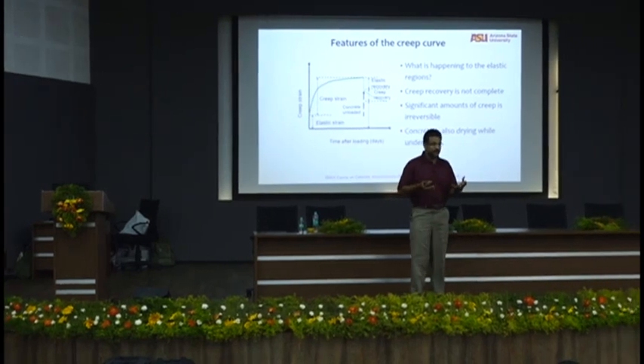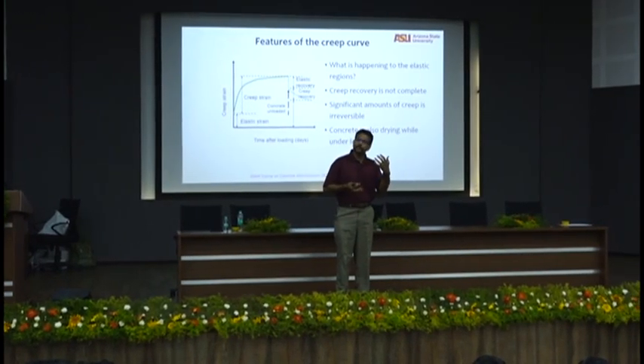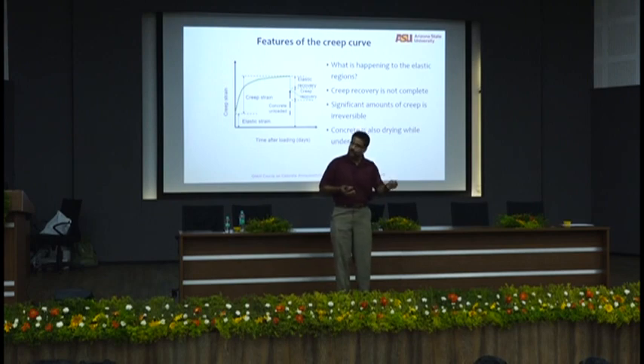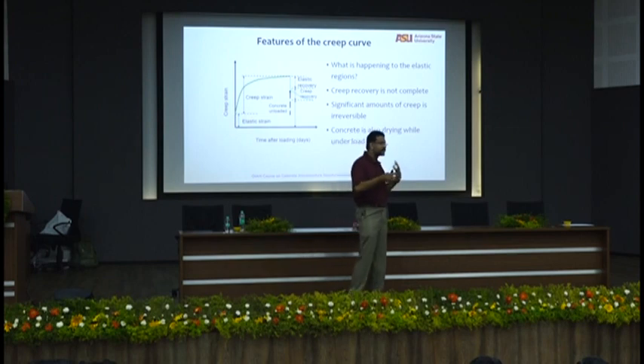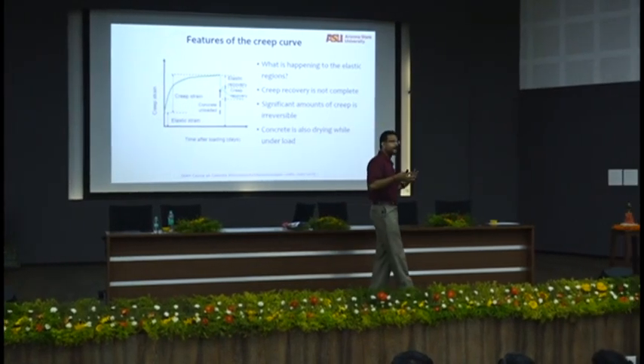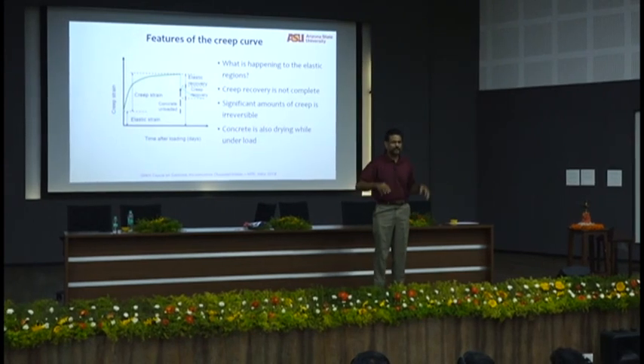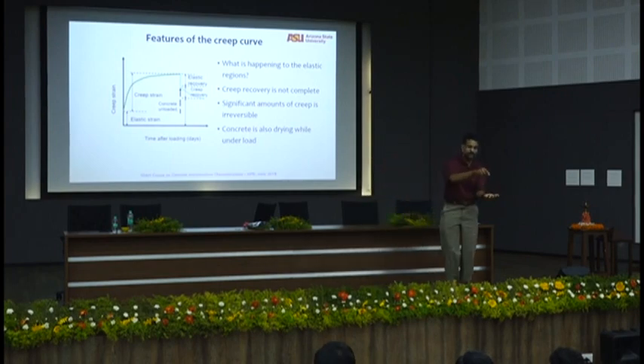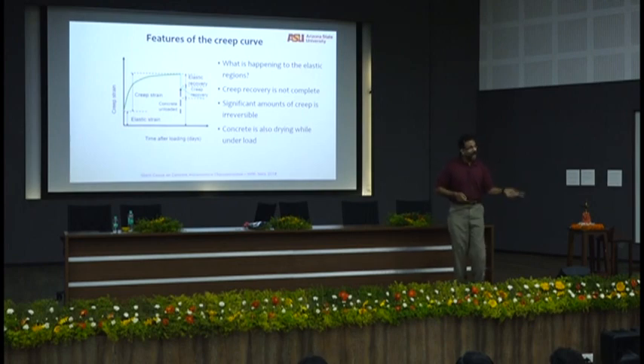Remember, your drying-induced volume change takes water away from the capillary. Assume that you have greater than 45% RH. Water goes away from the capillary, and then some local redistribution of water happens. Where is the only water available now? In the gel pores and around the gel pores. And then you have mechanical loading, high mechanical loading. What will happen to the gel water? It starts to squeeze out, shrinkage happens, right? Creep causes shrinkage. Creep causes loss of volume. And then add that to the shrinkage stresses already there, you get creep stresses. Cracking is guaranteed unless there is something to relax those stresses.